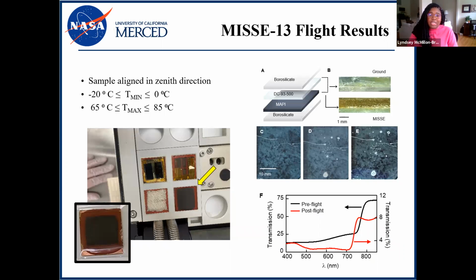So let's take a closer look at this sample. On the left is a photograph of the sample in the MISSE holder after the flight. And the inset is also a closer photo of the sample post-flight. We were already excited when it was returned to us and it was still black. That's a great indicator that it's the photoactive black phase of perovskite. So that was a great kind of canary for us.